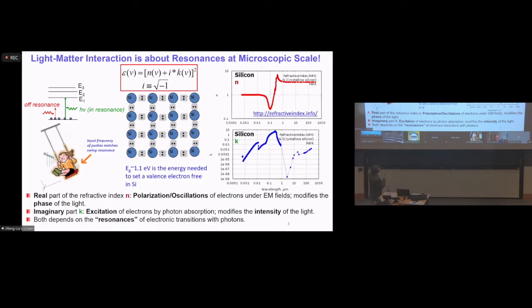So let's take silicon as an example. This little dot symbolizes valence electrons between two silicon atoms. As you know, each pair basically forms this covalent bond. And if you have a photon coming in with high enough energy, in this case greater than 1.1 electron volts, you can actually set one of those electrons free. So essentially, this electron carries negative charge. This deficiency of electrons, called a hole, carries positive charge. Essentially, when they move, they actually generate electrical current. That's the fundamental physical principle of solar cells and photodetectors we use today.